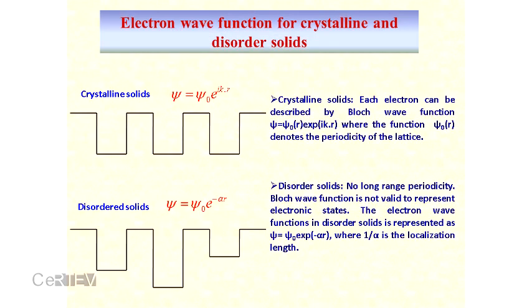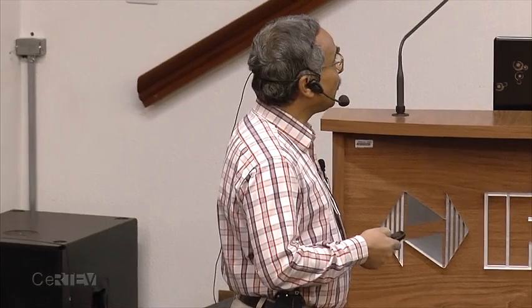To describe electronic properties, I must state the electronic states in disordered or glassy states. Because when an electron is moving in a particular material, since the electron is a quantum mechanical particle, it can be described by the so-called quantum mechanical wave function, the Schrödinger wave function. We can solve the Schrödinger equation. For crystalline materials, it is very easy because each atom can be represented by atomic potentials, which are of the same depth and same space periodicity. If we solve the Schrödinger equation, the consequence is that it is a periodic function.